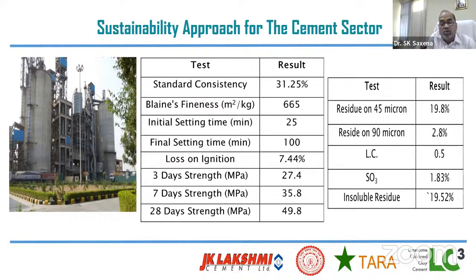And these are the compressive strength parameters at the different stages, like 3 days, 7 days, 28 days. And you will observe that it is as good as, or I can say good quality rather than other blended cement, which we achieved with this addition of clay and mica residue, etc. The residue which we kept on 45 micron was around 19.8% and 2.8% on 90 micron. There was no expansion, etc.